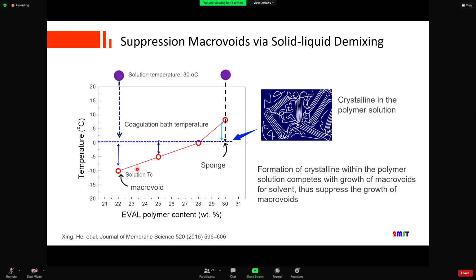So we have a large macrovoid. But for this polymer solution, you see here that the coagulation bath temperature is below the crystallization temperature of the polymer solution, which means the liquid-liquid demixing is largely constrained. Instead, the solid-liquid demixing is taking control. So we would expect fewer macrovoids, a more interconnected nanoporous structure.